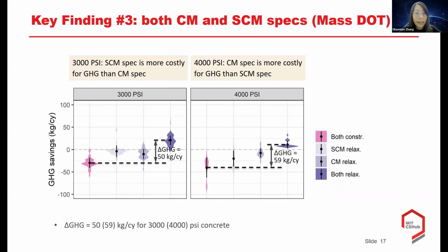And we investigate the actual GHG savings by comparing these four groups: the both constrained, SCM relaxed, CM relaxed, and both relaxed groups. When comparing the both constrained and the both relaxed groups, the ΔGHG is about 50 kilograms per cubic yard for 3,000 design PSI and 59 kilograms per cubic yard for 4,000 design PSI concrete mixtures.